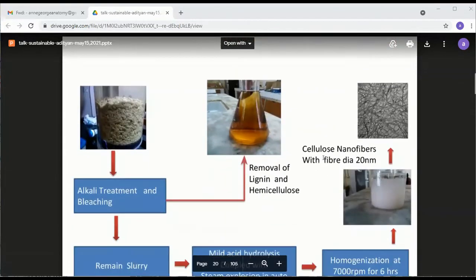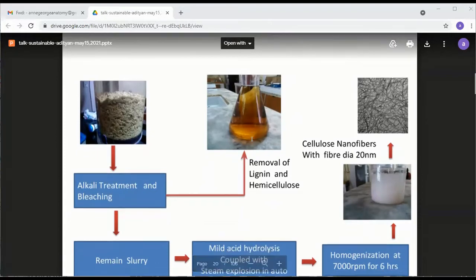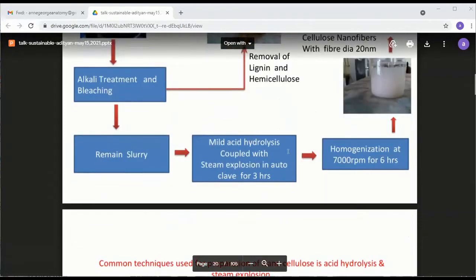Let me show you my next slide. The totality of the event, what we do in my laboratory: my PhD students go to the plantation, collect all this waste, clean them, dry them, and then we first subject them to alkali treatment. When you do an alkali treatment, you can remove lignin and hemicellulose. And then we get a slurry.